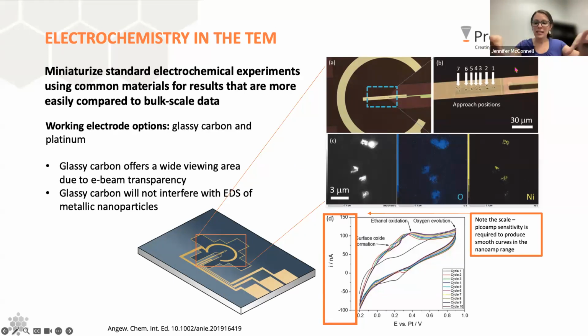And so you have a really nice wide surface area so that you can see what's going on top of it, and you're not limited to viewing only what's going on at the edges. Like with platinum, you're a little more limited, right? Because it's not so transparent, you're looking at what's going on at the edges. So if you're ever working with particles, especially platinum particles, the carbon is really nice because you can see right on top of the entire thing, and you won't interfere with EDS by having a platinum electrode and platinum in your sample somewhere. So glassy carbon or platinum are your options for your working electrode.